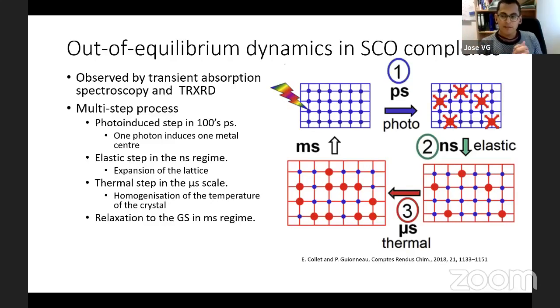But usually the energy we introduce with the laser is higher than necessary to produce this transition. So the excess of energy will also produce other changes. There will be some crystal expansion because of the excess of energy. There will start to be some heat or some propagation of the energy that will produce some elastic deformation in the crystal. And this elastic deformation will produce another transition from low spin to high spin. This is what is called the elastic step, which usually takes place in the nanosecond regime.